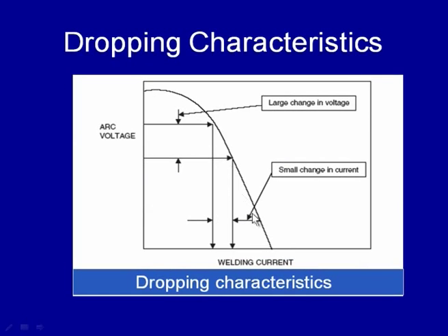This kind of variation in the arc voltage with the welding current, where we have a negative slope in the relationship between the arc voltage and the welding current, we call a dropping characteristic. Here, due to the fluctuation in arc length, if the arc voltage changes from this low level to the high level with the increase of arc length, then it will cause only a minor change in the welding current from this level to this level.